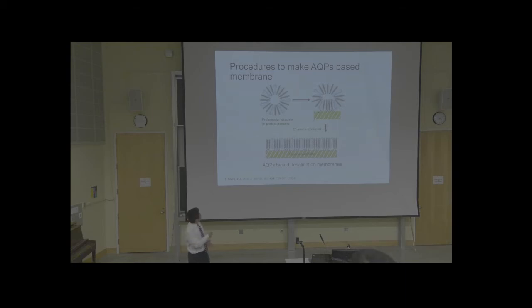Because we use sphere-shaped vesicles and we rupture them on the surface, this membrane suffers from a coverage problem. We can never get very good coverage of this material. So this membrane has a leakage problem. Besides, we also have other challenges of membrane proteins. So anybody got ideas? What kind of challenges?